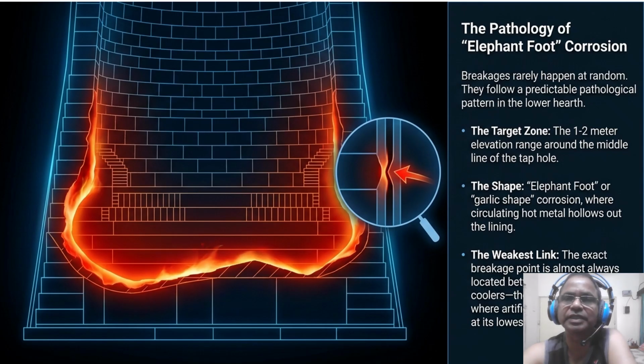Since we cannot see this with our own eyes, we have to rely on our thermal vital signs. So, monitoring the vital signs, the thermal threshold. Because the hearth interior is invisible, we use heat flux intensity as our proxy for proximity of molten iron. Follow the gauge from left to right. The safe zone is blue, but as we move to the center, we hit the warning zone at 35.8 kilowatt per square meter. At this point, your lining is severely eroded and intervention is mandatory.